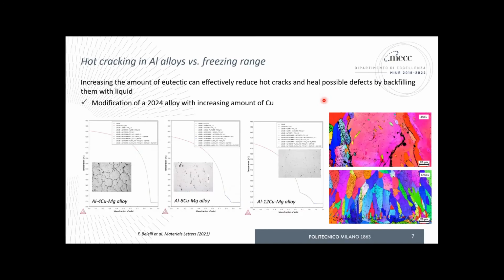Okay, this is another example. I was talking about the effect of adding more copper than the standard composition. It's an experimental work we did on 2024 alloy, the one that showed lots of cracks in the beginning. If we process standard aluminum 2024 alloy, so 4% copper and something like 1.5% magnesium, at the end of the solidification we got a lot of cracks. There's a network of cracks that makes the alloy unusable for any practical application. Okay, what can we do?